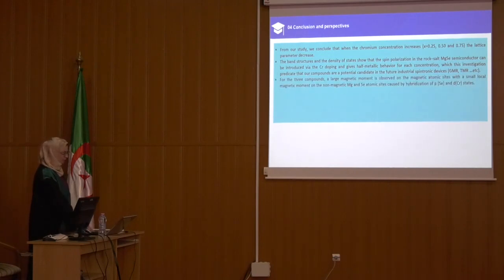For the three compounds, a large magnetic moment is observed on the magnetic atomic sites, with a small local magnetic moment on the non-magnetic Mg and Se atomic sites caused by the hybridization of p-Se and d-chromium states.